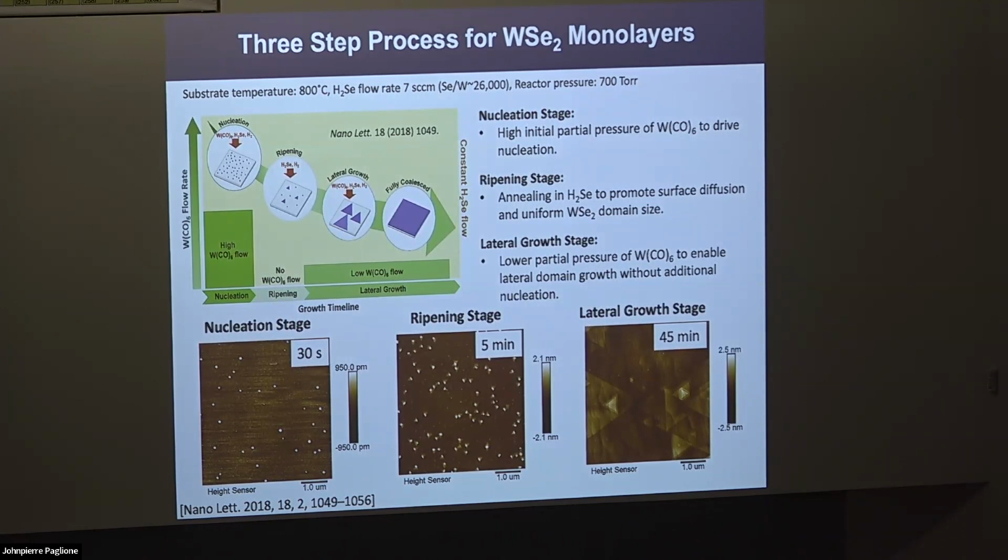Yes. Do the sapphire step edges affect the properties of your dichalcogenide? Yes. Actually, sapphire is a terrible substrate in that sense, because you have these modulations on the surface that constrain the layer, and that turns out to change the optical properties or the electrical properties. So usually you want a flat surface, like boron nitride. Actually boron nitride is a great substrate to grow these crystals. But these steps, at the scale of these monolayers, can really affect the properties. So yeah, that's an excellent question.